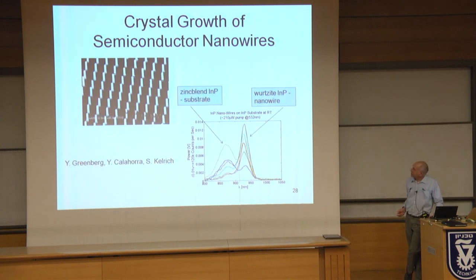A different subject is growth of nanowires. This work is done by Kobe Greenberg, John Calaro, and Sasha Kellrich. These are indium phosphide nanowires. It's quite interesting that they grow in the wurtzite crystalline structure. We can see here photoluminescence is at a different energy than the zinc blende substrate, higher energy. We can easily see it's wurtzite.